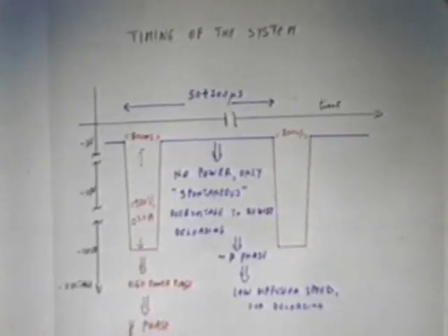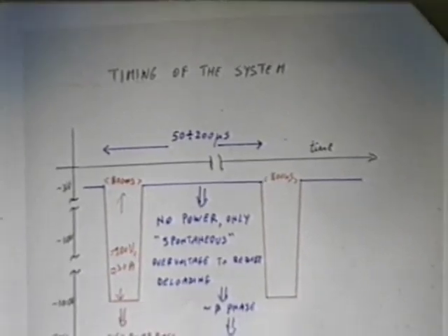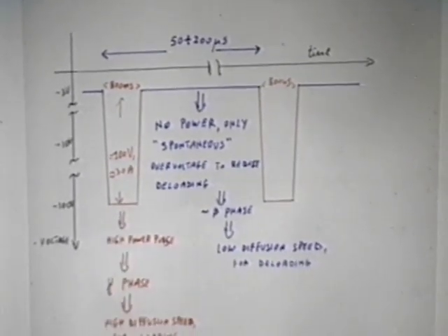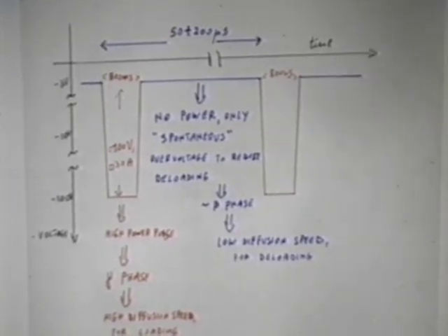A sketch of the system is the following. For a short time we give up to 100 ampere in the wire, meaning a current of the order of 1,000 to 100,000 ampere per square centimeter, very big numbers. And for another very long time we allow the system to deload, but not too much, to avoid the full deloading.